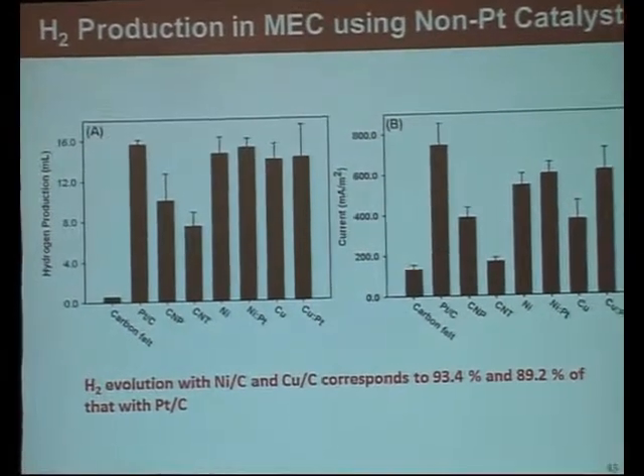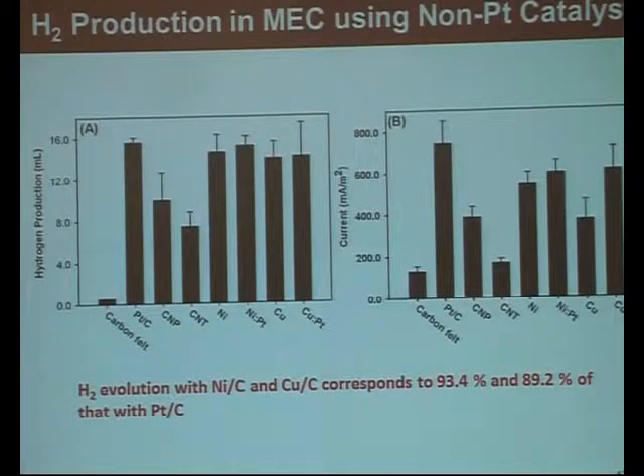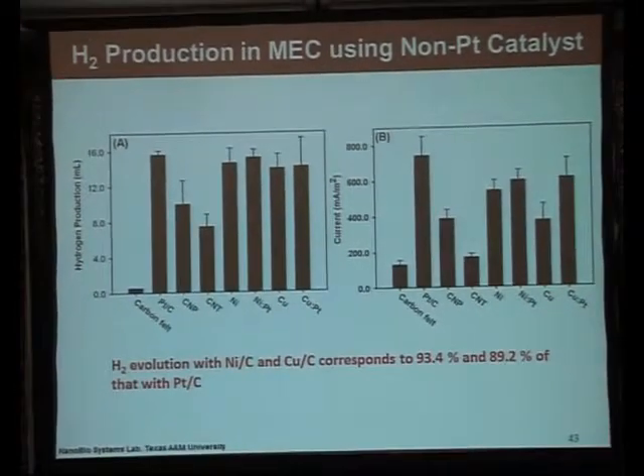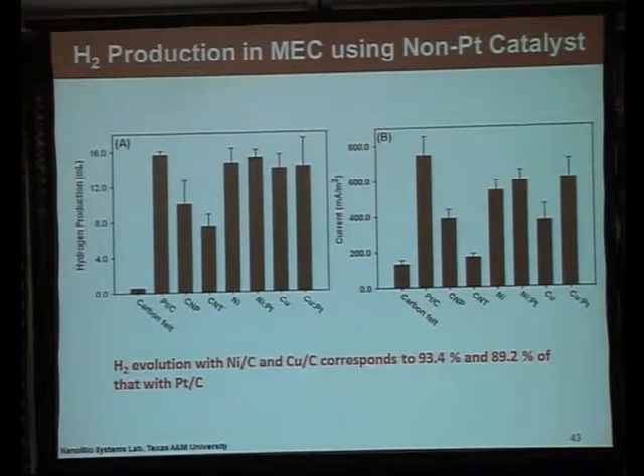Now this is very different from other type of hydrogen fuel cell that requires a very fast reaction rate. In microbial fuel cell, the rate limiting step is the microbe, not on the catalyst side. So what this one shows is, even though you're not using platinum, you can get a very high efficiency at a significantly lower cost.